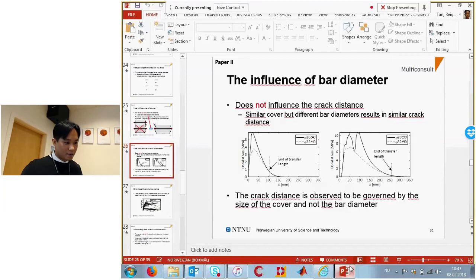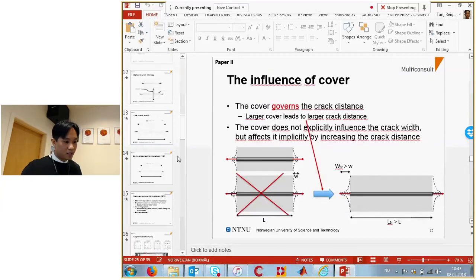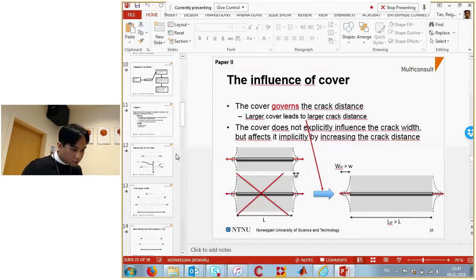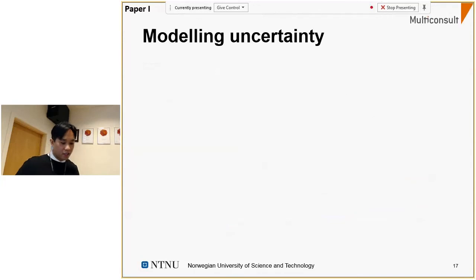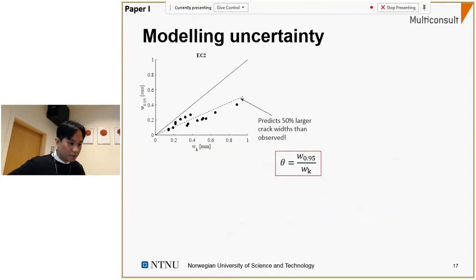As I pointed out in paper one, if we look at the modeling uncertainty of the formulas, the Eurocode 2 predicted crack widths that were 50% larger than what is observed. And note that we're talking about 50% larger than the maximum crack widths observed in the experiments, which possibly occur once or twice out of 100 observations. In the Norwegian Public Roads Administration, we have to use covers that are up to 120 millimeters for bridge structures that are exposed to marine environment.